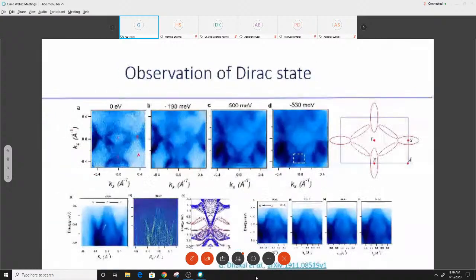This slide contains our main ARPES result, and in the first figure we show the Fermi surface map and energy contours. The Fermi map shows a central diamond-like structure. You can also see a diamond-like structure at the A point, and the energy contours show the evolution of band structure with binding energies. The right side shows the schematic drawing of the Fermi surface.